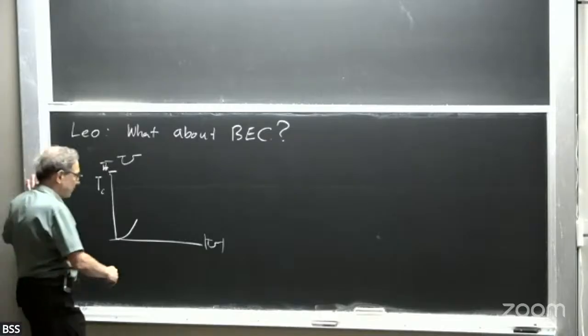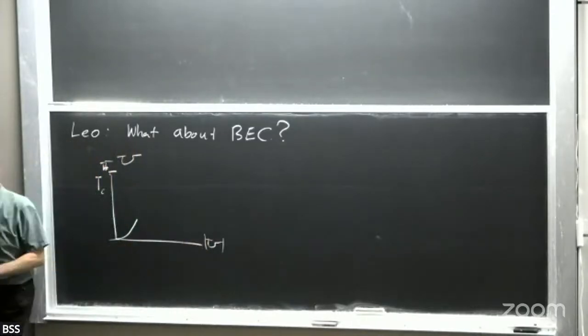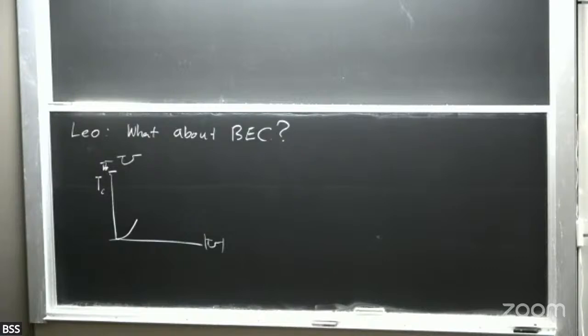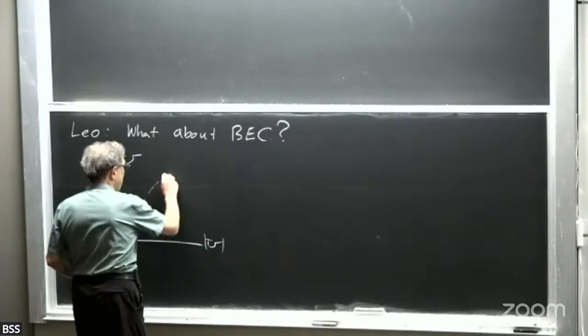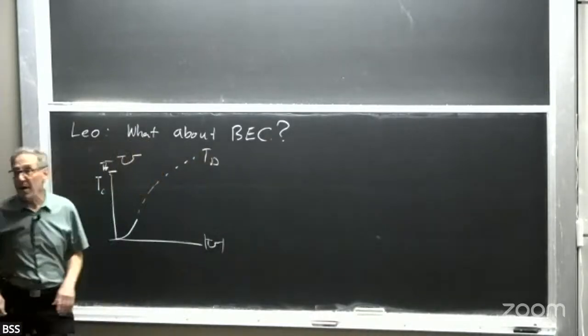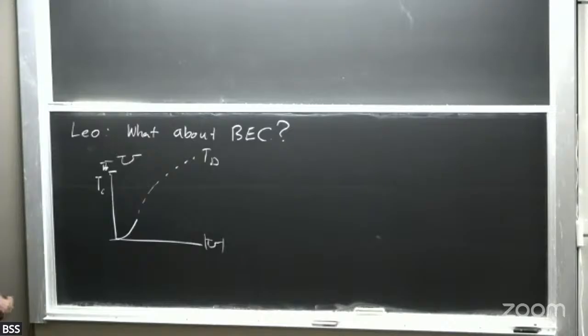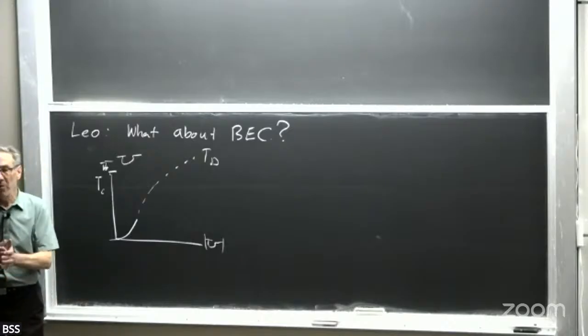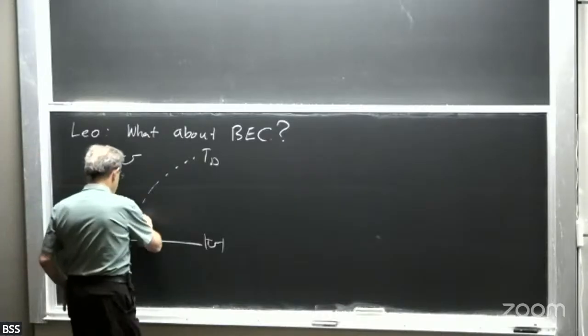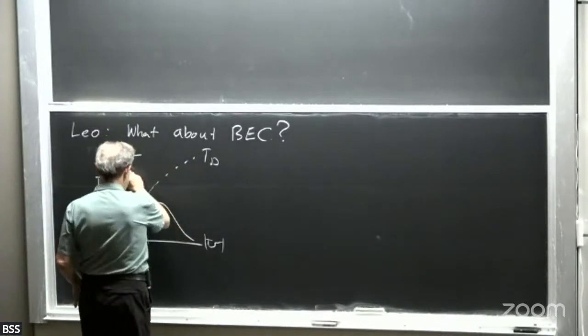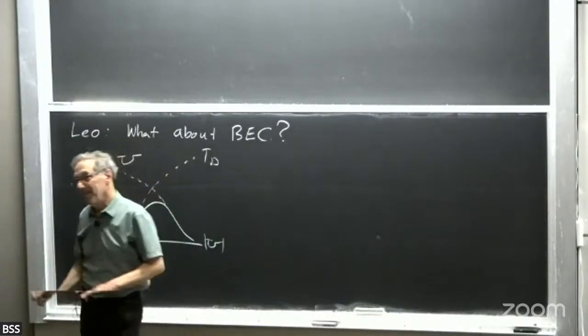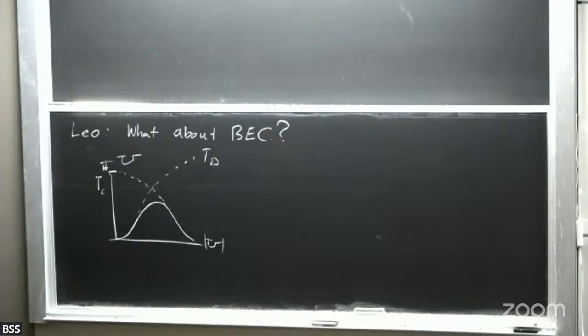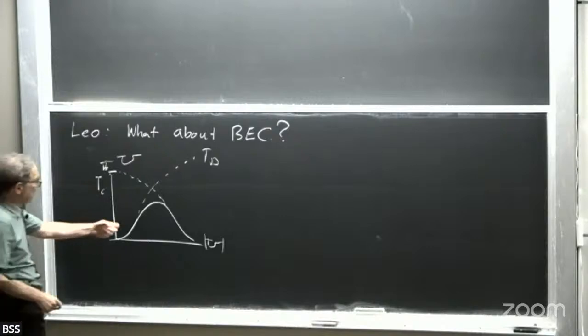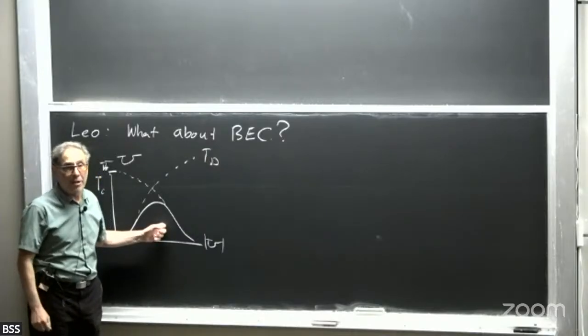On the other hand, if U is big compared to E Fermi, then you form real space pairs. You have pairs of electrons on a site, and the pairing scale goes through the roof. It goes linearly with U. On the other hand, the pairs can only hop at order t squared over U. So Tc does this, and T theta does that.